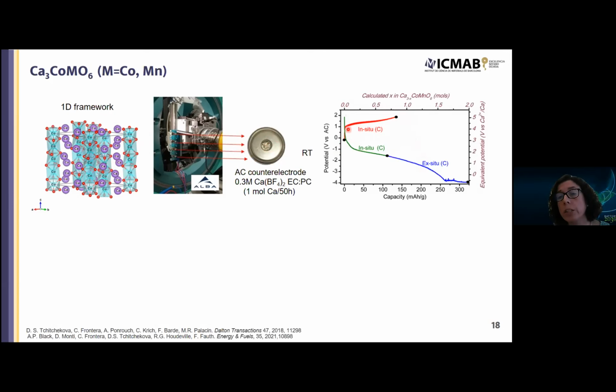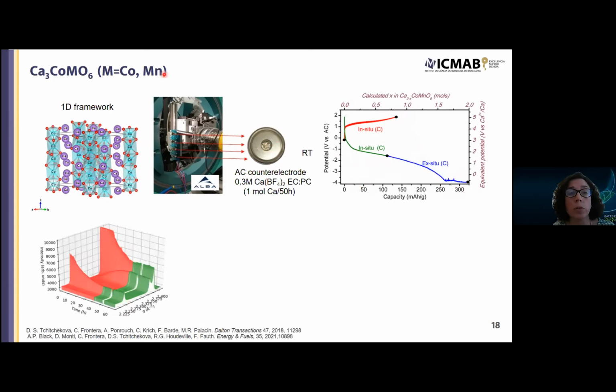So we get the oxidation, and then we get the reduction, and then we were able to further reduce again the cell and take some patterns at the end. And the result is the same for the cobalt and for the cobalt manganese compound. This is what we get. Upon oxidation in red, the pristine phase amount starts to decrease, and a new oxidized phase appears. But then upon reduction, as you see, there is nothing going on, and I don't have the blue pattern here, but it's exactly the same one as the green.